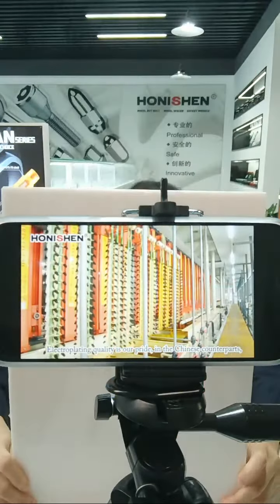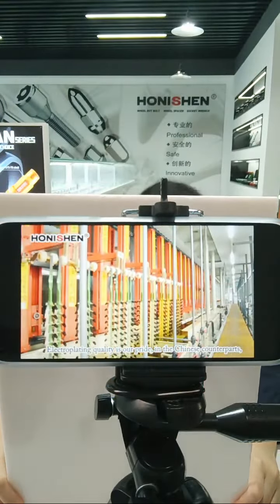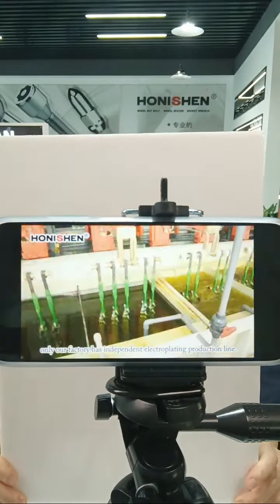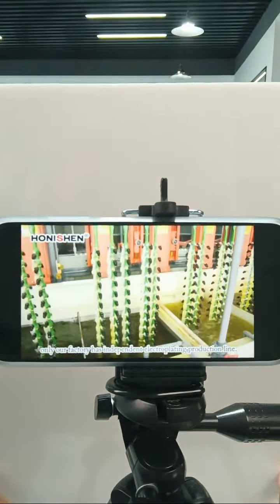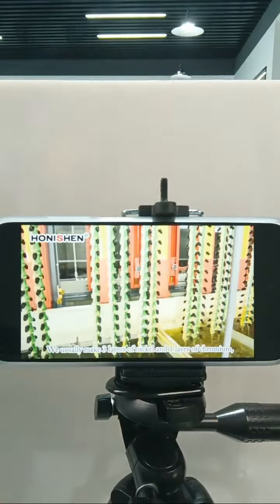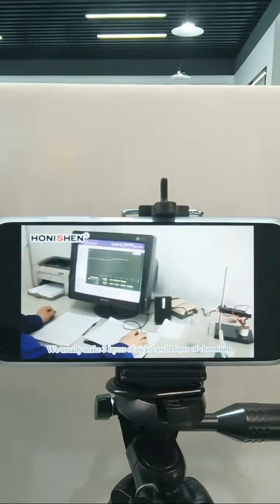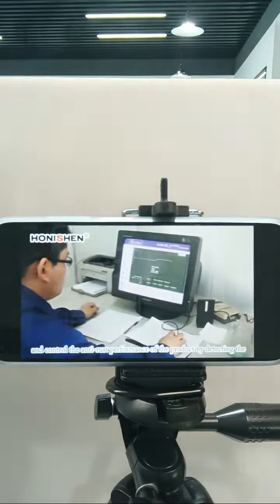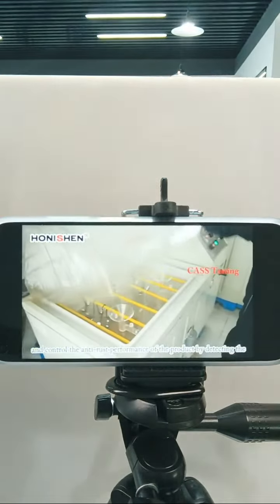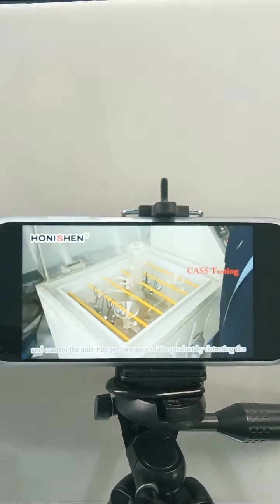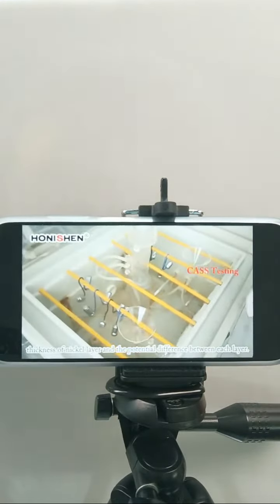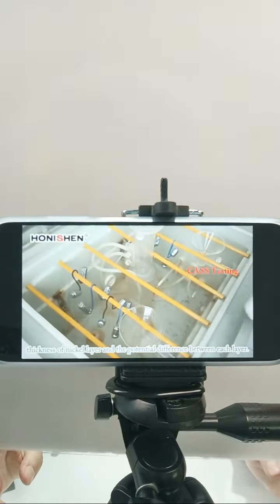Electroplating quality is our pride. Among Chinese counterparts, only our factory has an independent electroplating production line. We usually make 3 layers of nickel and 1 layer of chrome, and control the anti-rust performance of the product by detecting the thickness of the nickel layer and the potential difference between each layer.